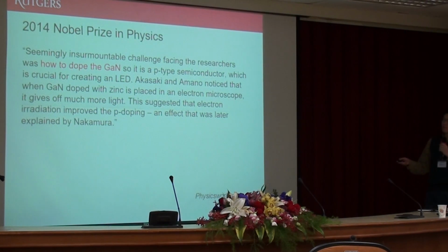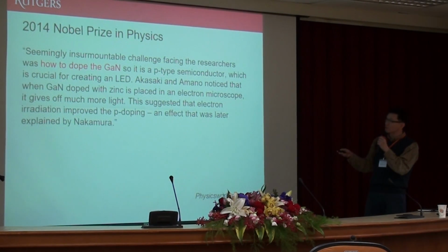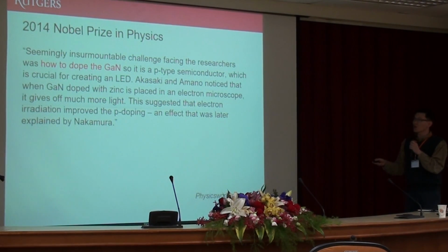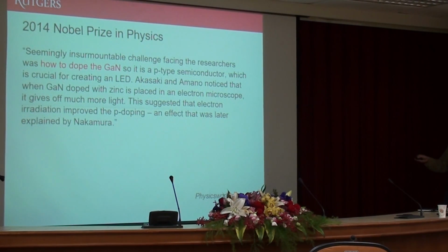early 1960s, but people were not able to make gallium nitride into any diodes because they were not able to dope, they were not able to p-dope gallium nitride. So when Professor Akasaki and Amano demonstrated that it could be doped by zinc somehow, and then it was really further clarified by Professor Nakamura that the p-doping could be done reliably, and then it has become possible to make blue LED, and that's why we have all the light type being replaced by